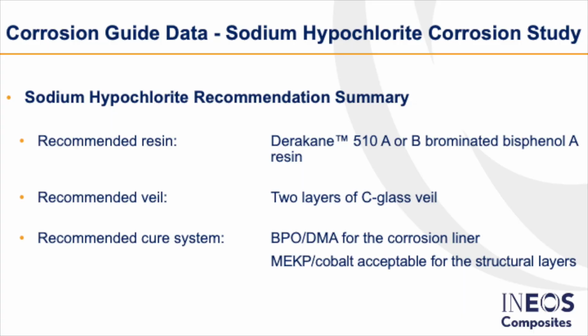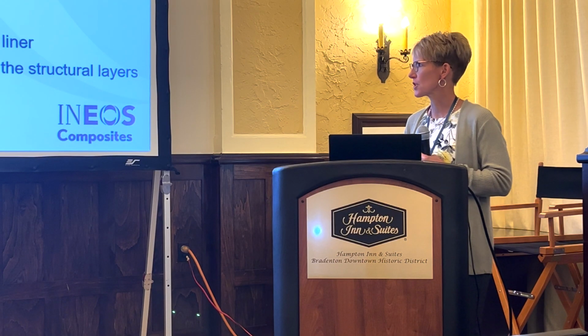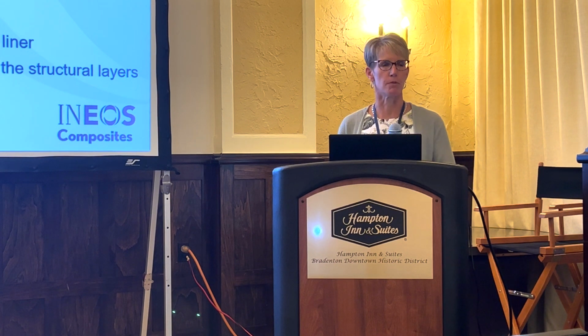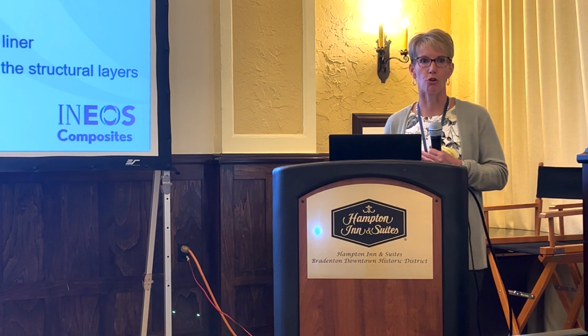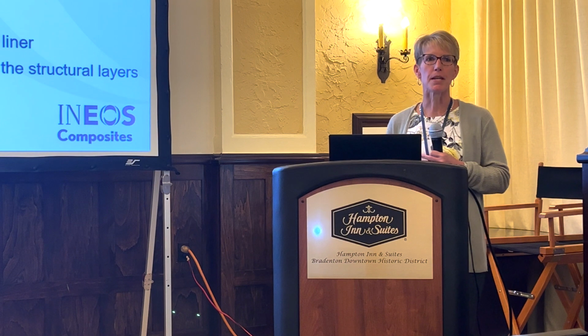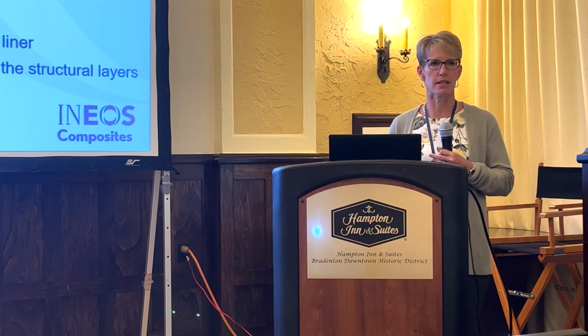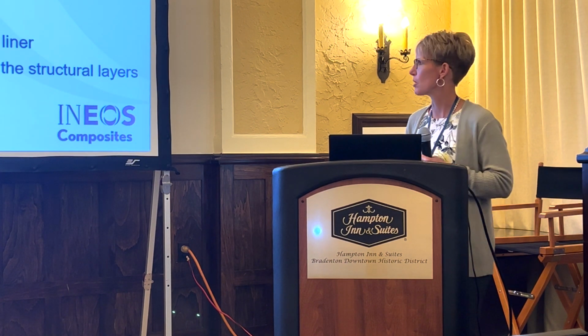So this just summarizes what we just went through, with the recommended resin being a Derakane 510 series, the brominated. The Derakane 411, the standard bisphenol A, is suitable for the lower temperatures and the lower concentrations of sodium hypochlorite. Your recommended veil, generally 2 layers of C glass. And then the cure system, as I talked about, the BPO-DMA is going to be the optimum system and recommended for that corrosion liner. Cobalt MEKP can be used in the structural portion just because that's not going to be directly exposed to the sodium hypochlorite.